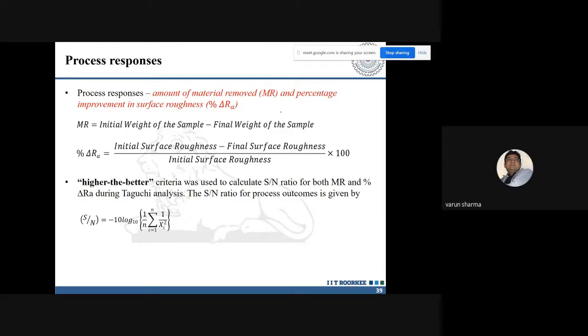That is the initial weight of the sample minus the final weight of the sample, and whatever is the difference over there, that difference has gone into the abrasive media, because that has become a part of the media that was moving from the upper cylinder to the lower cylinder. The other one was the percentage improvement in the surface finish. That was initial surface finish minus final, upon initial, into 100.